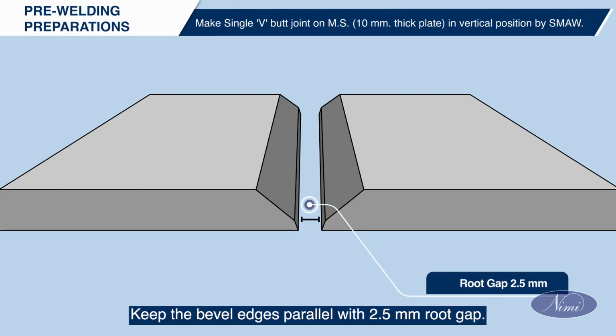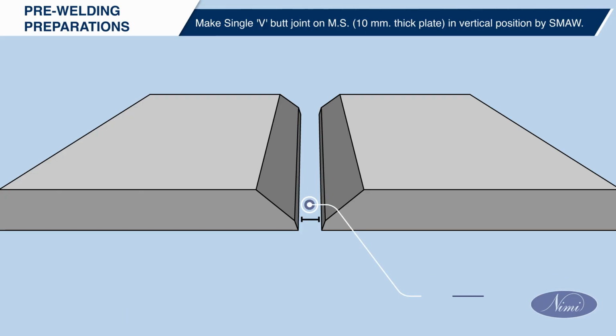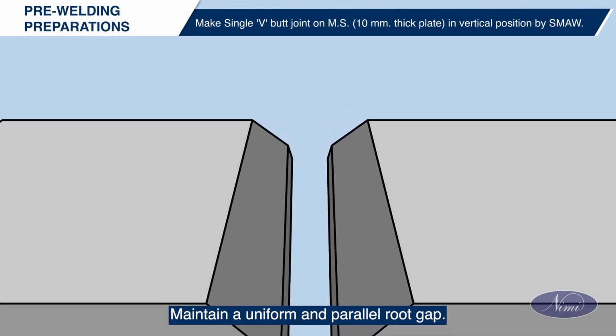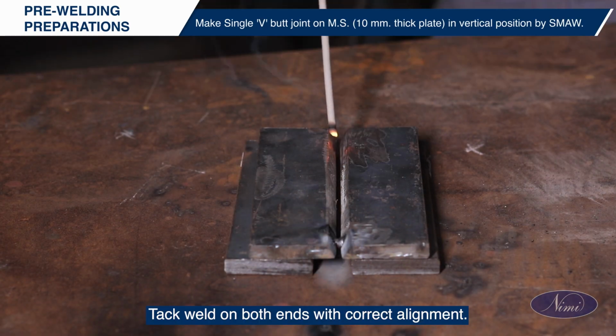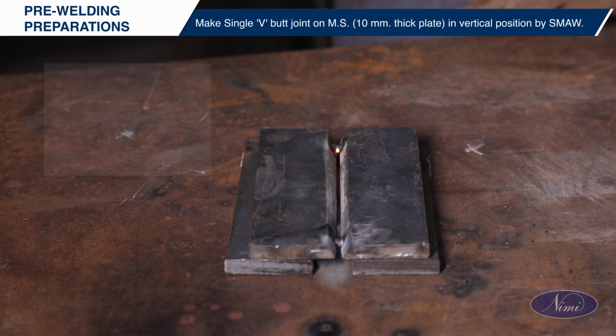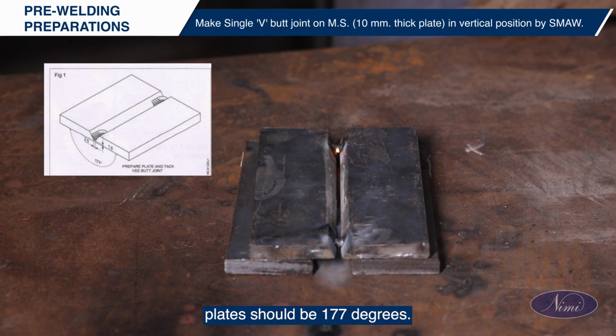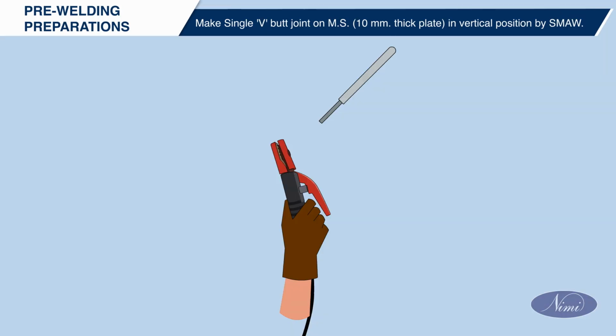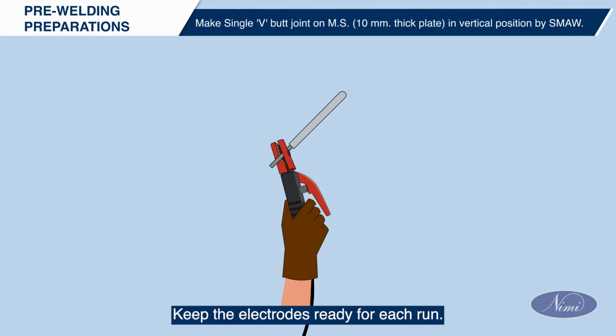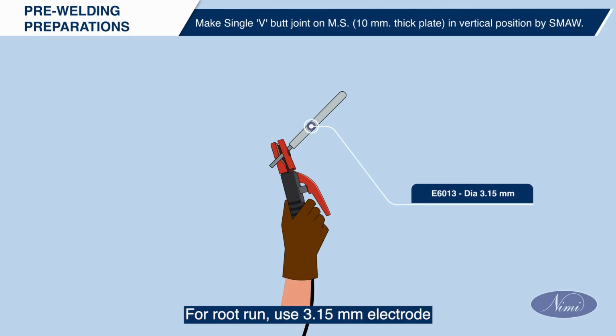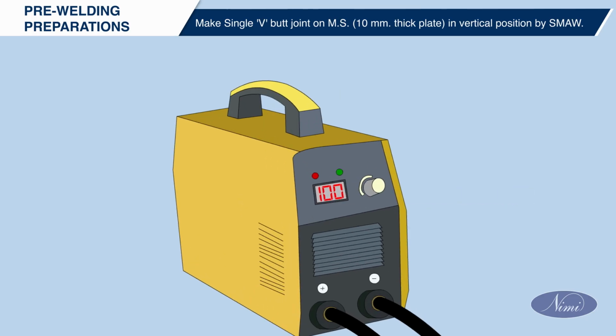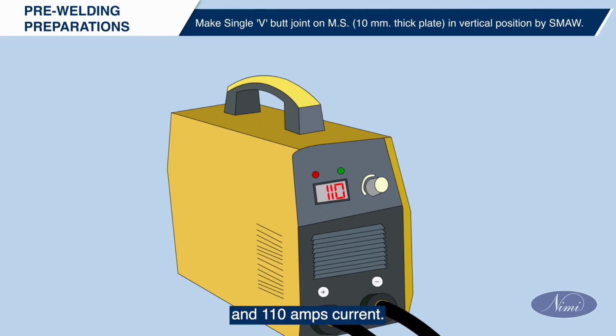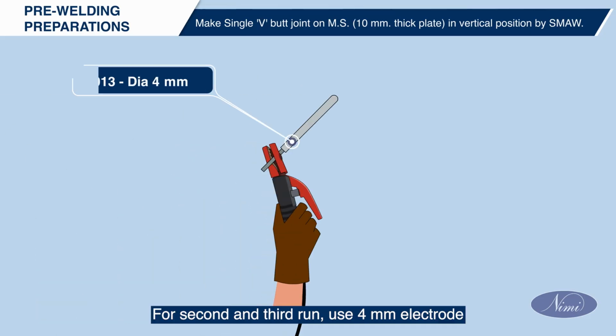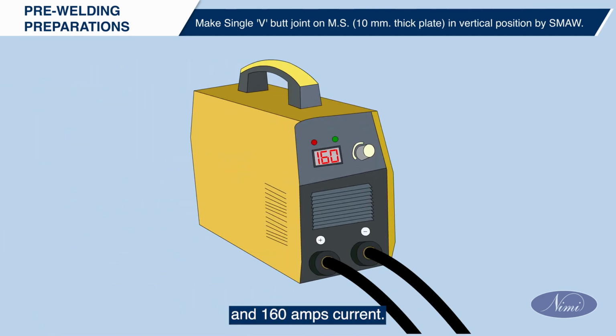Keep the bevel edges parallel with 2.5 mm root gap. Maintain a uniform and parallel root gap. Tack weld on both ends with correct alignment. The root side angle between the plates should be 177 degrees. Keep the electrodes ready for each run. For root run, use 3.15 mm electrode and 110 amps current. For second and third run, use 4 mm electrode and 160 amps current.